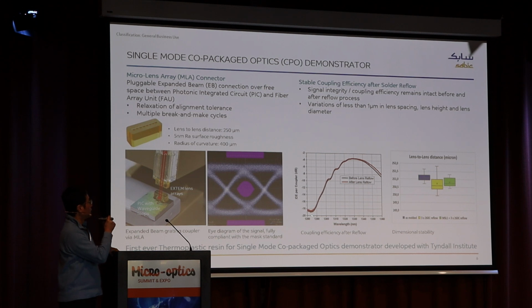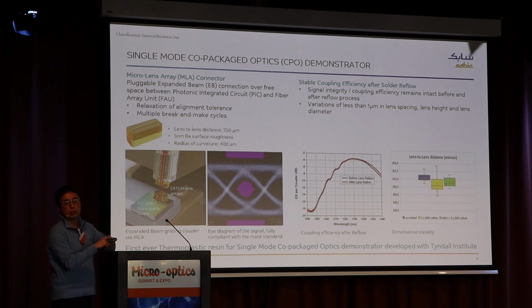Also, after reflow, you can see they are almost overlapping each other. Here we also measured the lens geometry using metrology. After 3 times reflow, even at MSL1 condition, you don't see much dimensional change. By the way, MSL is the moisture sensitivity level before the reflow process in the semiconductor industry. All the electronic packagings are shipped in a sealed package, and once you open the package, how long the part can withstand or reabsorb moisture before going to the reflow process. So our material can withstand MSL1.